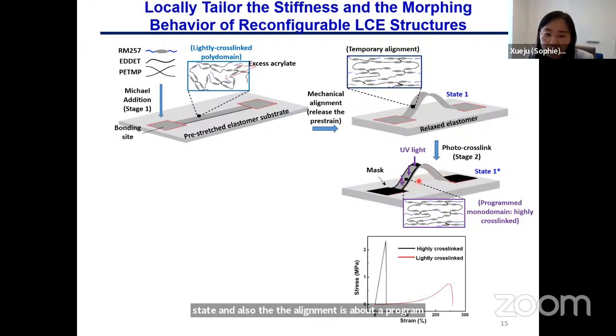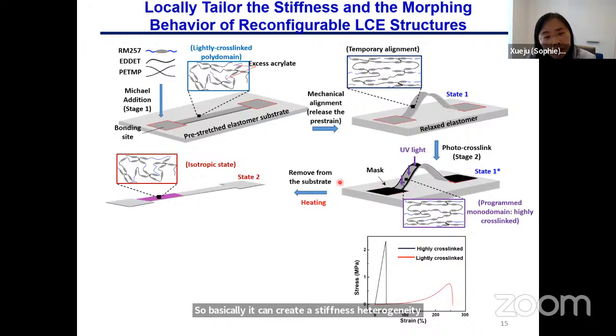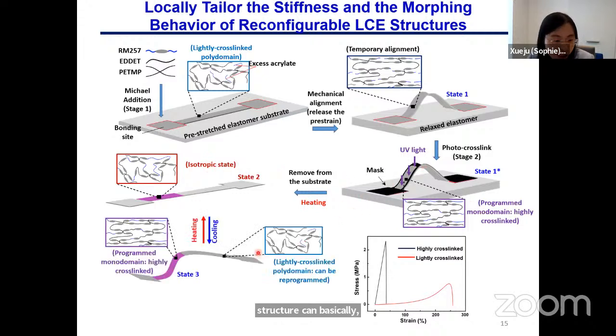Okay, so in addition to the difference in cross-linking density and mesogen alignment in the UV exposed and covered regions, they also have a stiffness difference of almost 50 times between the highly and lightly cross-linked regions. So basically, it can create stiffness heterogeneity within the same structure. After being removed from the substrate and heated, you can see that the structure morphs to the 2D configuration because of the isotropic-nematic state transition. But when it cools down, what is interesting is that driven by the shape morphing in the UV exposed region, which is highlighted in purple, the structure morphs into an asymmetric structure with heterogeneous stiffness, with the purple region almost 50 times stiffer than the gray region, which is lightly cross-linked.